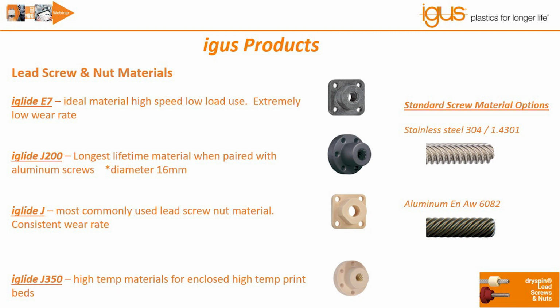Now, as we're increasing the load, we do have some other materials that are going to work a little bit better. So our J200 lead screw nut material is best when it's paired with an aluminum lead screw. And this actually has some of the best wear rating and wear resistance across all of our lead screw and nut material combinations. The only caveat to this is the fact that aluminum lead screws typically are rolled here at igus at 16 millimeters in diameter and up. Then we have our most commonly used material, iGlide J. And for more specialized applications, for example, a 3D print bed where the lead screw and the nut are enclosed in the bed itself where they might be subjected to higher temperatures, we have what we call iGlide J350.